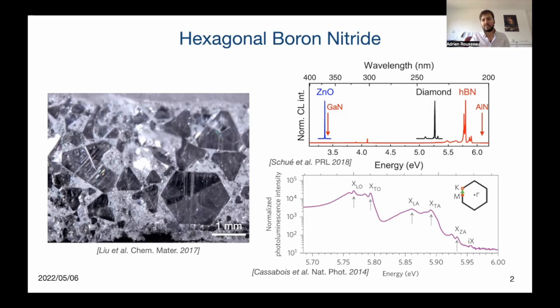One of its amazing properties is that it shows a strong luminescence in the deep ultraviolet at a typical wavelength of 200 nanometers, which makes it a great candidate for deep UV optoelectronic application. More interestingly, its intrinsic luminescence in the deep UV comes from the anomalously strong phonon-assisted emission of its indirect bandgap, whereas the intrinsic emission of indirect bandgap semiconductors is generally very weak.